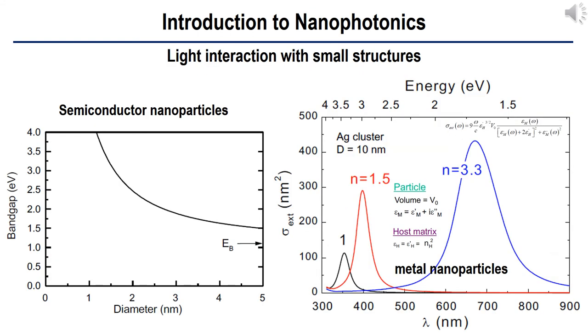For molecules, light scattering occurs due to a harmonically driven dipole oscillator. For nanoparticles, there are different mechanisms: for insulators, Rayleigh scattering occurs where the scatterer size is much smaller than the wavelength of light; for semiconductors, resonance absorption occurs at light energy greater than the band gap energy and size-dependent fluorescence can be observed; for metals, resonance absorption occurs at the surface plasmon frequency with no light emission. For microparticles with size larger than the wavelength of light, there is enhanced forward scattering allowing an intuitive ray picture. For microparticles, we observe Mie scattering and rainbows due to dispersion in water droplets, with many applications including resonators and lasers.